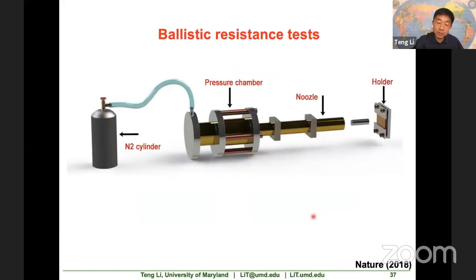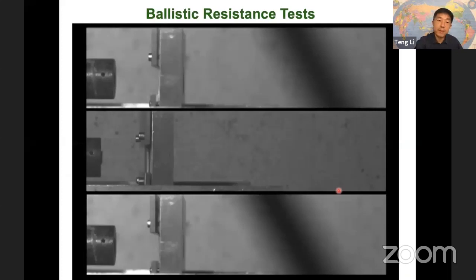So we also did the ballistic resistance test, or the energy absorption test. This is the illustration of the air gun. It will shoot a steel bullet out of this nozzle, and the wood piece will be here. And we have a Phantom high-speed camera to take the video. Let me show you the video here. So this is a video taken from the side, perpendicular. So the wood sample is here.